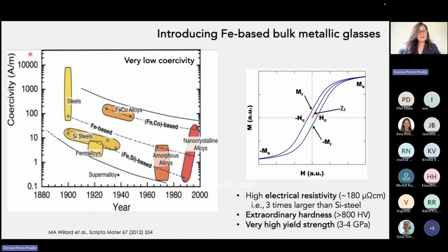And I want you to take a look here to this graph on the left, where we plot the coercivity for different types of alloys. Here we have the silicon steels. And then here, within this darker orange domain, we have the iron-based bulk metallic glass. Of course, there is a wide variety because we have many compositions that are possible and many ways of manufacturing them. But these materials in this fully amorphous state have the potential to have a very, very low coercivity and therefore to reduce the magnetic losses. But not only that, because of this disordered nature, they also have extremely high electrical resistivity. This is 3 times larger than that of silicon steels. So if we are able to use these materials to manufacture, for example, a rotor, we would also be simultaneously able to reduce eddy current losses.